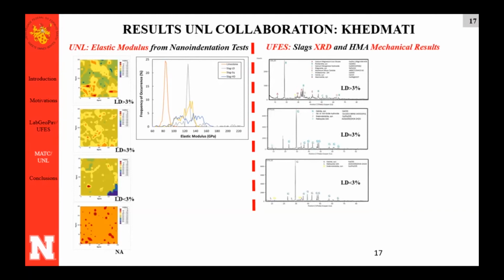So I just compared with the chemical results that I had from Brazil from X-ray diffraction. And we also observed from the X-ray that we had many chemical components for the high level of expansion. And after curing, we have a kind of stabilization of the chemical components. So the results match. But I was still interested in how this will affect the mechanical performance of my mixtures. I have the answer why it varies, maybe because of the chemical changes, but how this could affect the asphalt mixture performance, that's my main question as a civil engineer. I want to use the material and see how this can affect it.